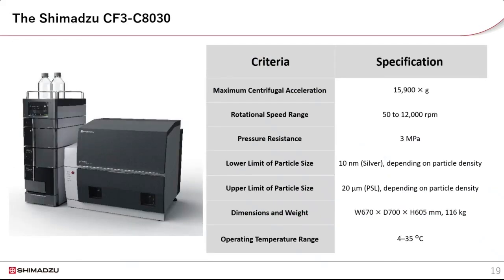And now, introducing the Shimadzu CF3 C8030 Centrifugal Field Flow Fractionation System. It is capable of analyzing a wide range of particle sizes, and it offers the best resolution using centrifugal forces of up to 15,900 Gs or 12,000 RPM. The Shimadzu CF3 is the first to achieve lipid nanoparticle separation using CF3.